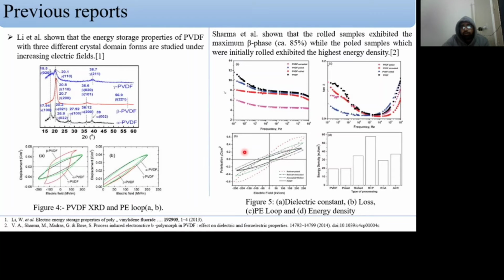So Sharma et al. We can see that when we anneal the PVDF, the dielectric constant is decreased, and as it is rolled, the dielectric constant also decreases. But the polarization is increased. In this case, we can see the polarization is increased for the rolled PVDF and annealed PVDF.